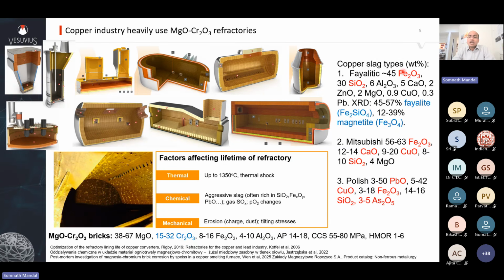And a big challenge of these applications is the very high amount of slag, a very acidic and very corrosive slag. So you see fayalitic slag contains about 45% iron oxide. This is a very common slag grade, and then 30% silica. And then if you do XRD of the solidified slag, you see that about half of it is fayalite, and then a big chunk of the remaining one is magnetite. And then there are some furnaces like the Mitsubishi process and some other newer variants where they use a calcium ferrite slag. This slag is very corrosive, being a very low viscosity slag.